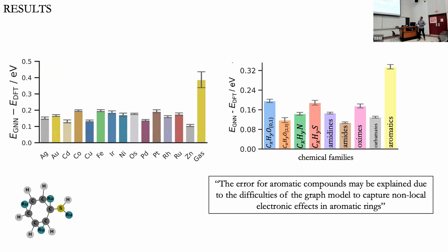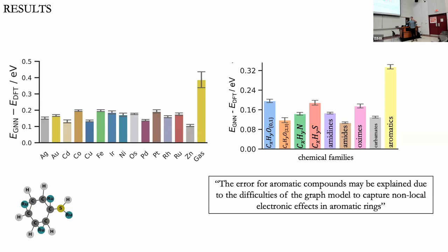We started with a 3D graph: we did DFT, geometry optimization, and ended up with a structure. Catalysis research has developed good algorithms to identify which metal atoms interact with the adsorbate. Based on those algorithms, we built the molecular graphs for training data. For the same molecule with different optimizations, we found copper connected differently — sometimes only to a carbon, sometimes forming a bridge between hydrogen and oxygen. These different geometries are all included in our dataset, representing different states.